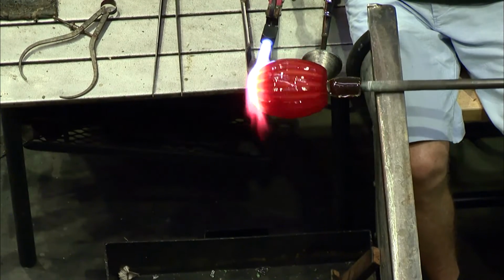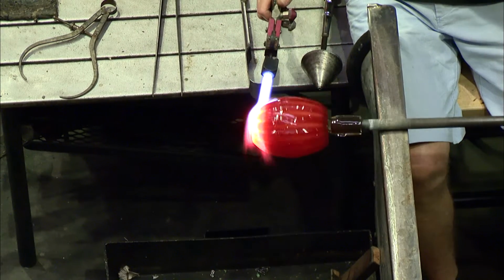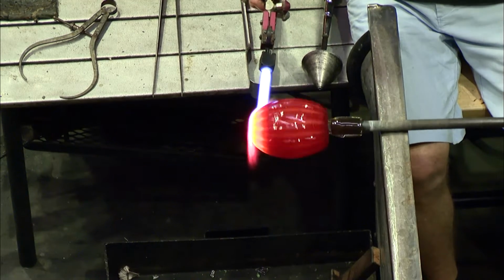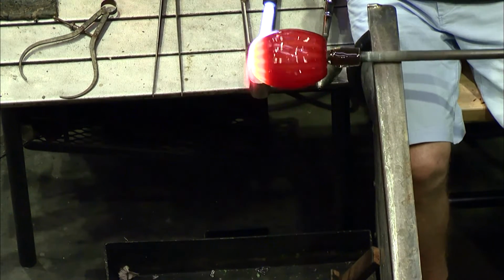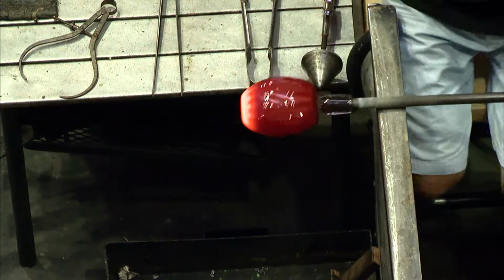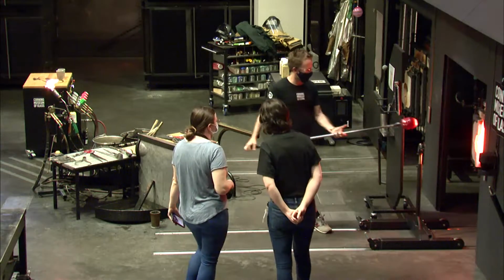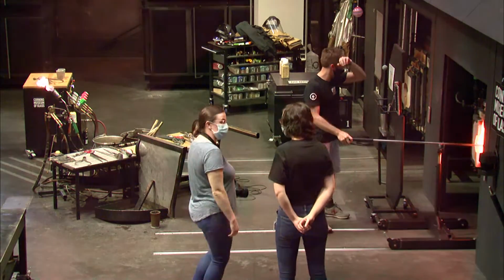So after we transfer a piece, we do a pretty significant reheat because in order to break the piece free from the blowpipe, we have to get it close to that threshold for cracking and breaking, or thermal shock, which is roughly about 1,000 degrees Fahrenheit. So that reheat, right after we transfer it, we're bringing it back up to a workable temperature closer to 2,000 degrees Fahrenheit. So it usually takes a bit of time.